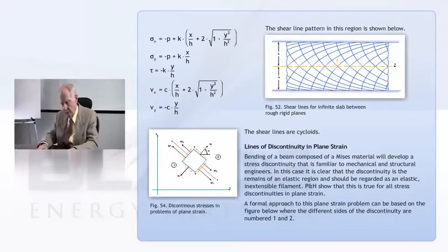The only thing that can be discontinuous is this interior normal stress. It's written as N1 and N2 with primes on it. And so now we're back in that same old situation where we have the two intersecting Mohr circles, and one side of the line is one of the circles and the other side of the line is the other circle. Going to the next slide.